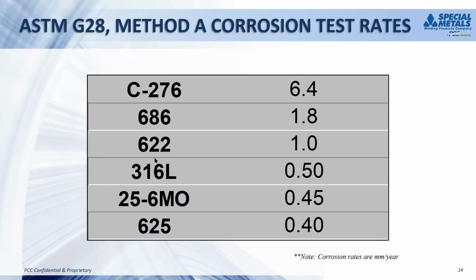If you notice, C276 has the highest rate of any of the materials in this list. In fact, the 3 highest are the 3 most corrosion resistant materials, nickel, chrome, moly, tungsten materials that we know work very well in FGD systems. The 3 lowest rates are 316L, a super austenitic, and alloy 625, and we know that these materials do not have nearly the corrosion resistance of the nickel chrome molys. So you can see you get erroneous results by trying to use that type of information.